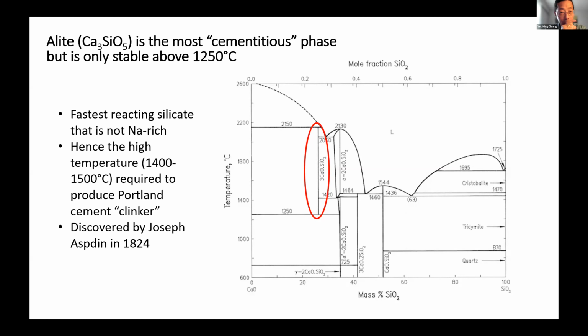Now, sodium silicates are water soluble, but high sodium, or high alkalinity in a cement is not the same cement. It's actually a different kind of cement that may have some uses, but is not widely used. It's not Portland cement. So aside from sodium silicates, this calcium silicate, the alite phase, is considered the most cementitious phase because it's the fastest to dissolve and the fastest to react to form calcium silicate hydrate. And so this I'm showing you to highlight the second part of the problem, which is, how might one get around these thermal processes, right?